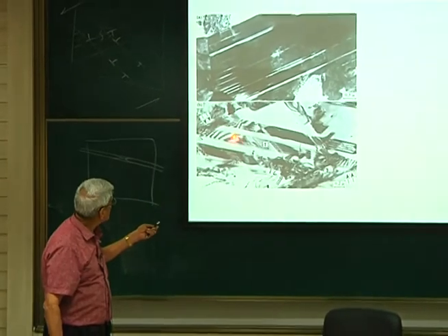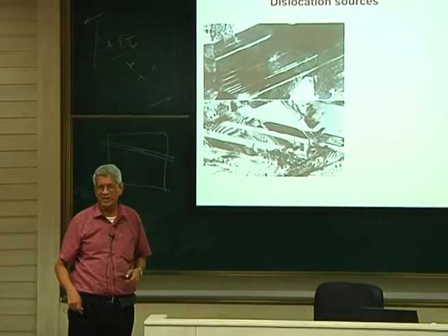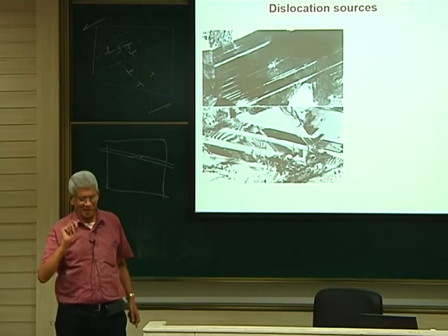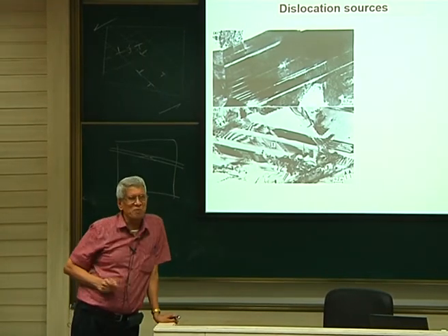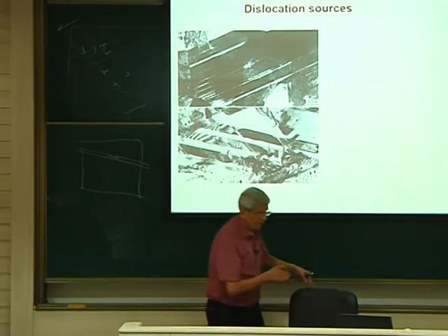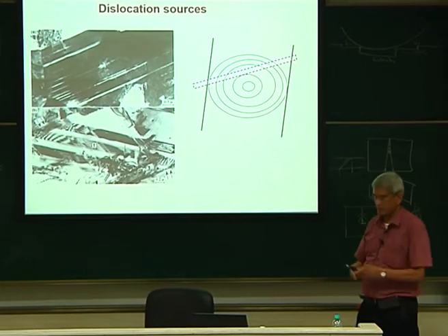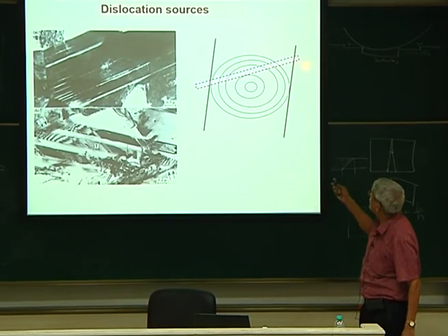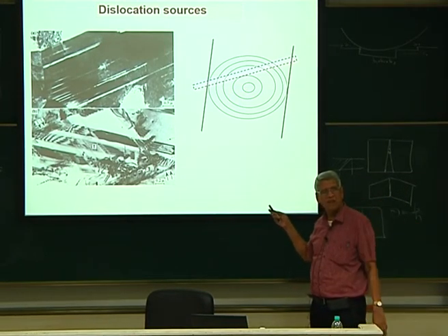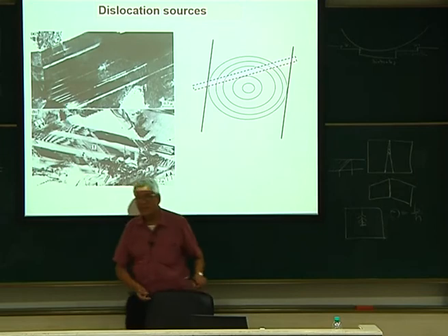Okay, you can see that the dislocations have come and are hitting this surface of the boundary, and the dislocations are hitting on this side also. And what we noticed is that we could not see frankly any dislocation source within this boundary. Then we thought that the way this sort of microstructure could form is only by a sample where this is a sort of a foil. The source may be outside, the source is in the bulk, but not in the thin foil, but the effect is what we are seeing. This happens quite often.